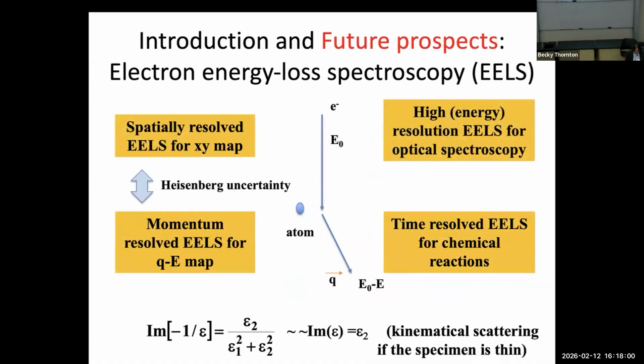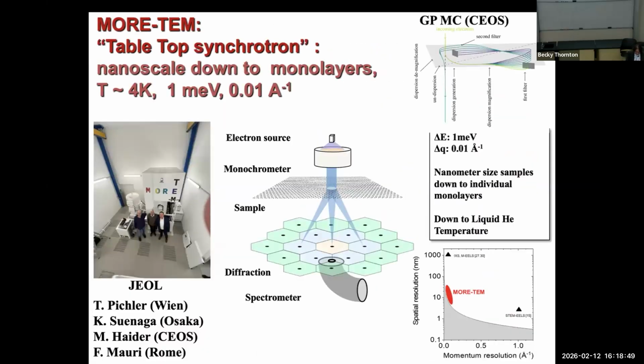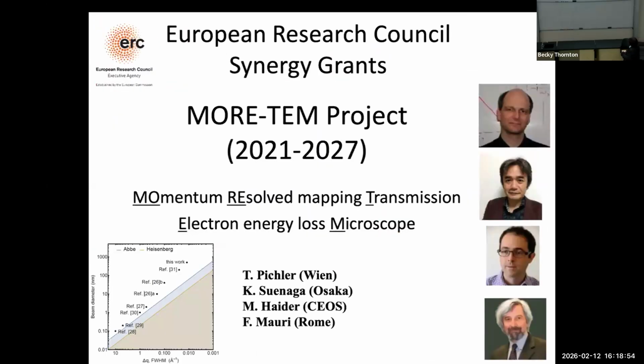This is my final slide. As I told you, for the spatial resolution and the momentum resolution, this is a complete trade-off. It's the Heisenberg uncertainty, so we cannot get both pieces of information together. The energy resolution and time resolution are also very much limited, because if you want good energy resolution, you need a longer exposure time. But we are trying to find more compromise conditions to realize such tracking of reactions inside the nanotubes.